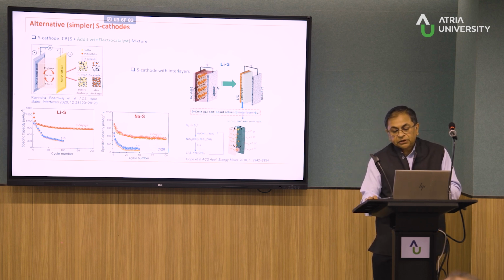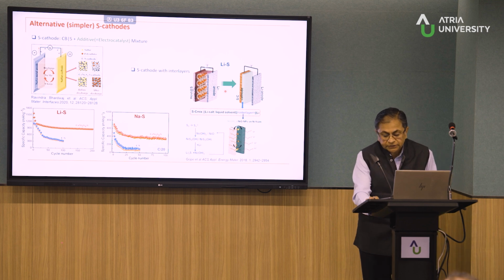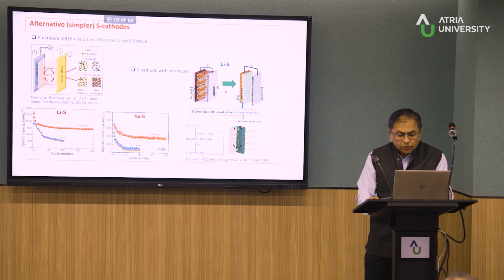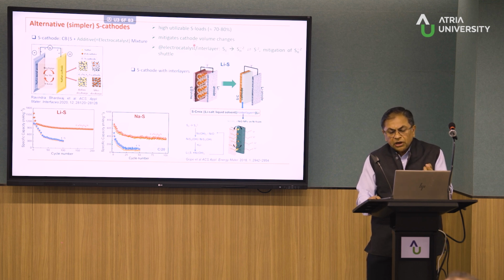Okay, so this does a wonderful electrocatalytic reduction of sulfur to lithium polysulfide, lithium sulfide, and back. Okay, and the important thing is, you get loadings which are pretty high. You can go as high as 10 milligram per square centimeter loading in these kinds of systems. So the advantage here is you now actually have some hold on the reaction.